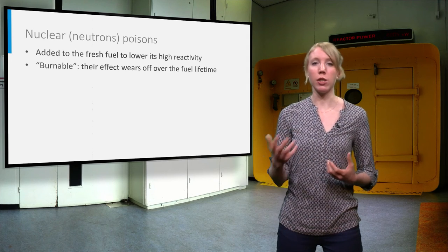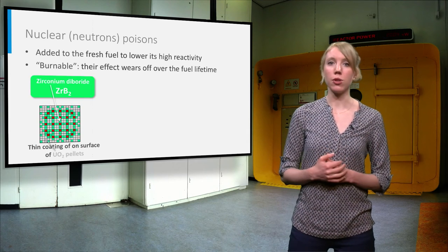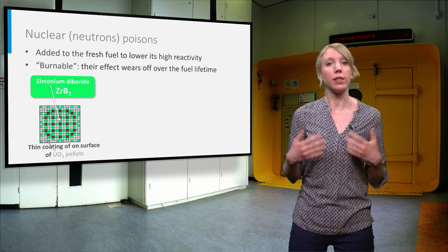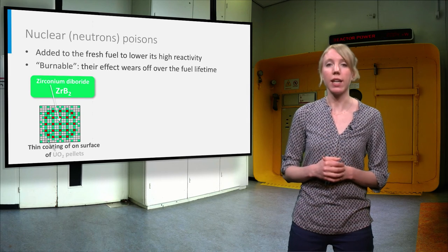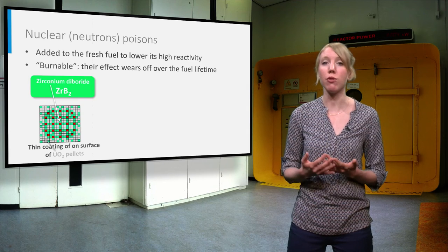Boron and gadolinium are commonly used in light water reactors. Boron is used in the form of zirconium diboride, which is applied as a thin coating on the surface of some of the uranium dioxide fuel pellets.